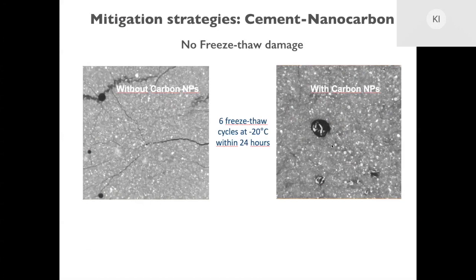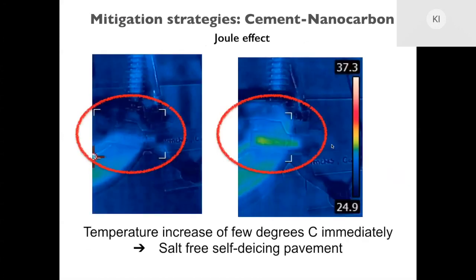And on top of this, this material has the so-called Joule effect. As long as we plug it in on a small voltage, we can increase the temperature of the material. Here you see by 5 degrees, but on recent results, we can go even to 100 degrees.